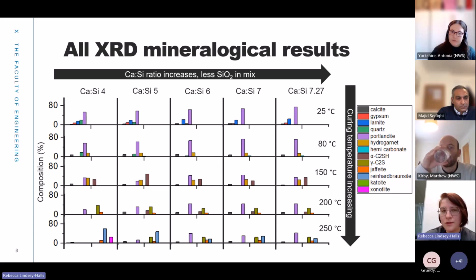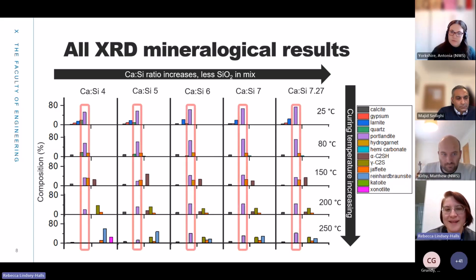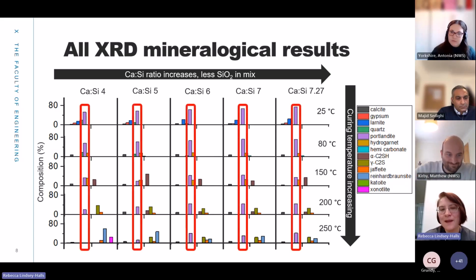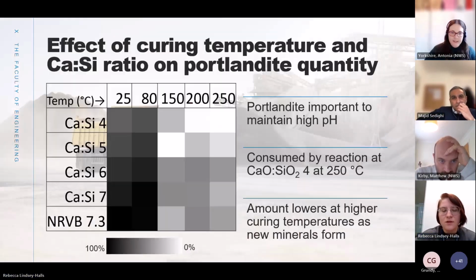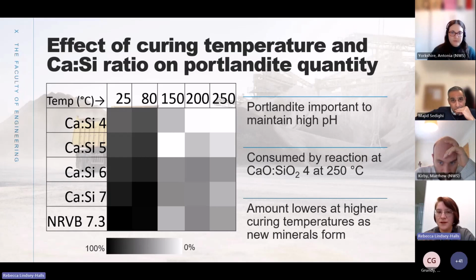So I'm just going to talk through a couple of the minerals here that I think are interesting. The one I've highlighted is the portlandite. This is the calcium hydroxide that is responsible for the high pH. Here's a heat map showing the amount of portlandite, where black is 100% and white is 0% present. As you can see from this, at a calcium silica ratio of 4, so the highest amount of silica dioxide addition, at 250, there is no portlandite left.